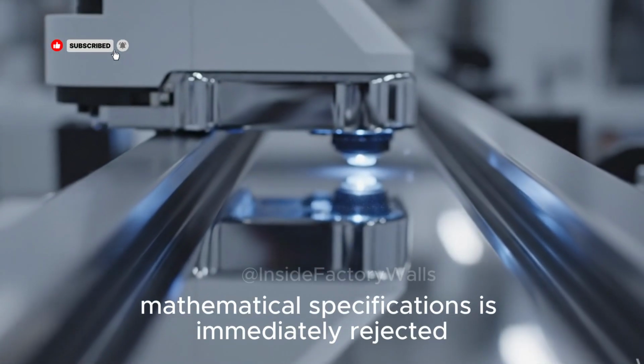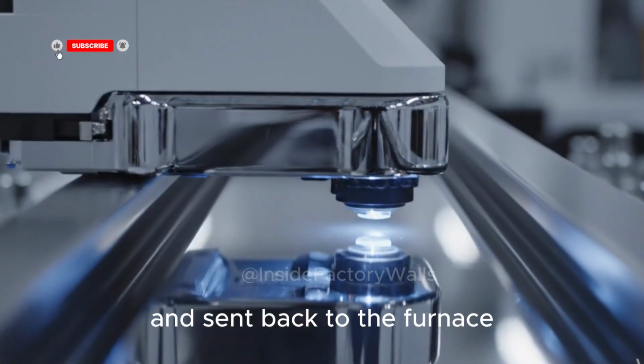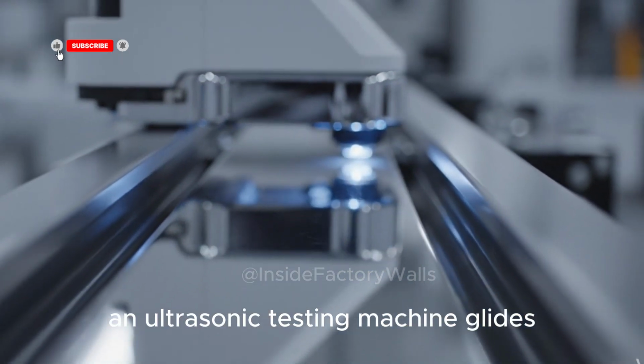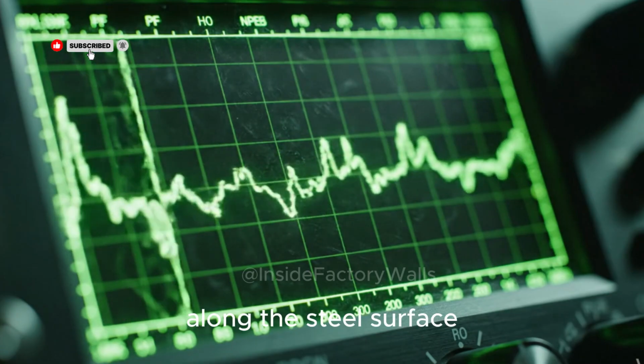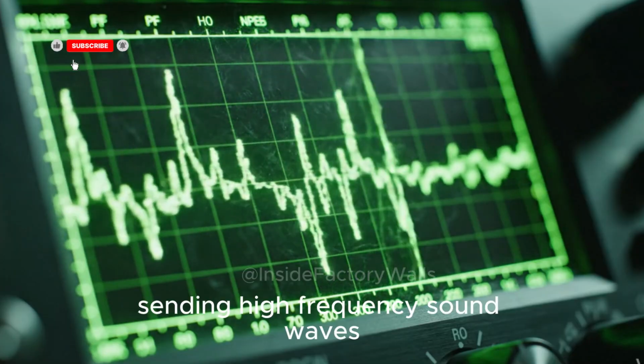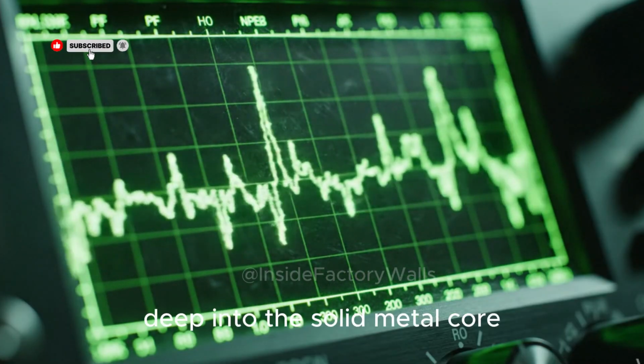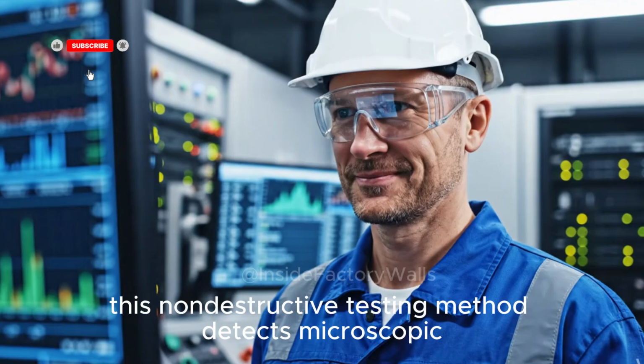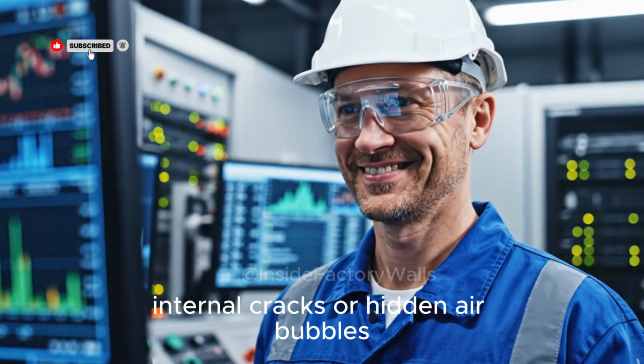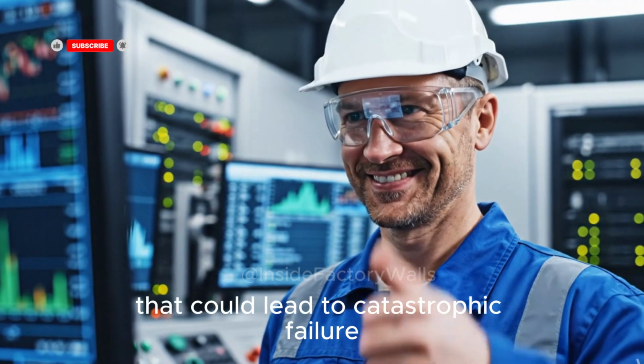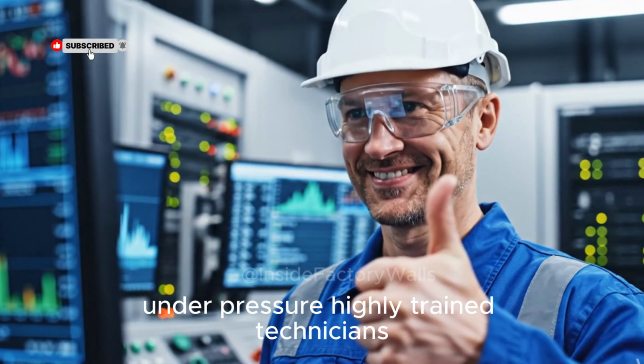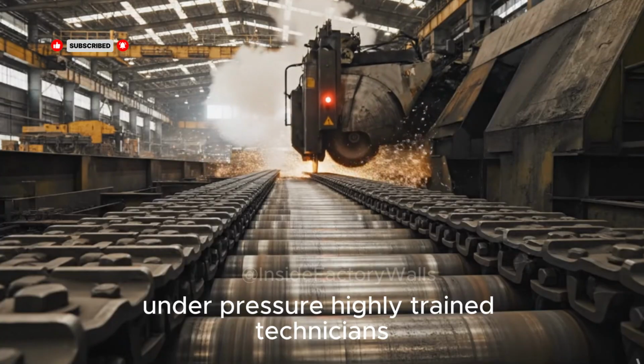the track. Automated laser scanning systems measure the dimensional profile of the rail, verifying that the width and height meet strict international standards. Any rail that fails to match the exact mathematical specifications is immediately rejected and sent back to the furnace for remelting. Next, an ultrasonic testing machine glides along the steel surface, sending high-frequency sound waves deep into